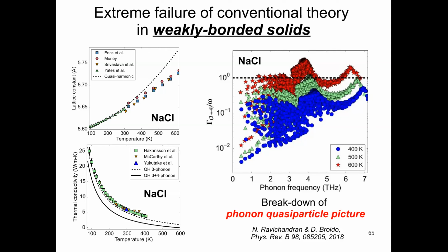Okay, so you mean to say the boundary determines the scale, and essentially 4-phonon scattering is no longer... That really depends on the material and temperature, right? If you go to low temperatures and if you take something like diamond, the mean free path is several millimeters long. But if you take sodium chloride at 600 Kelvin, the mean free path is a few nanometers. Right. Okay. So if your device is comparable to that mean free path, it will be affected by diffuse scattering at the boundary. Good. Thank you.